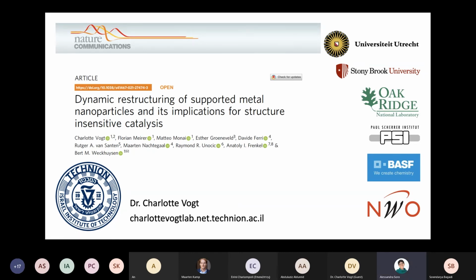Yeah, so the first one is, how were the in situ TEM samples pre-treated prior to their exposure to the ethylene gas mixture? What are the condition boundaries of the in situ TEM chips? So if I'm not mistaken, those chips have pretty good heating, you're able to heat them up to I think about 800 degrees. We used 500 degrees because we know for our nickel nanoparticles that that is enough to reduce them fully, and we kept it there for 1 or 2 hours, I forget.